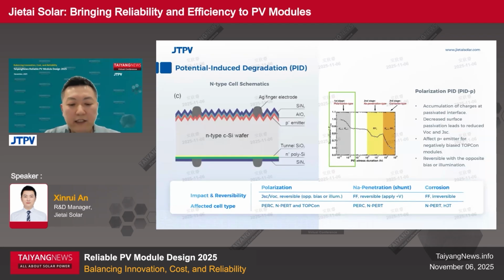And the third type, the potential induced degradation (PID), is caused by the potential between cells and the module frame, which is usually grounded. And it was first discovered in p-type modules as increased shunting. However, 3 progressive stages are identified for n-type modules, and each of them has a different level of impact on different cell types. The first stage is the polarization type PID, or PID-P. It's caused by accumulation of charges at the passivated interface, and it is usually manifested as a decreased surface passivation that leads to reduced VOC or JSC for the cell. And PID-P can occur with either positive or negative bias.